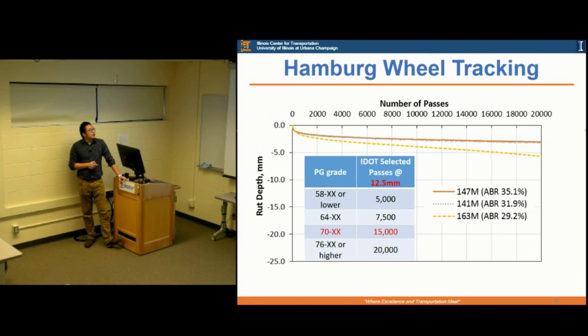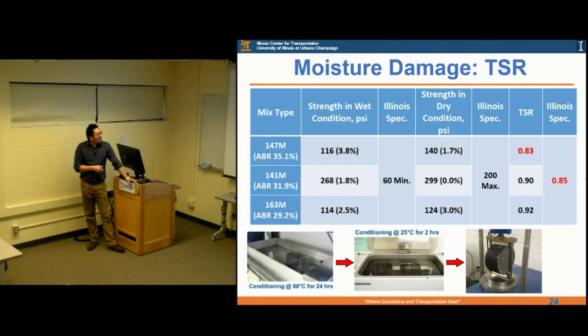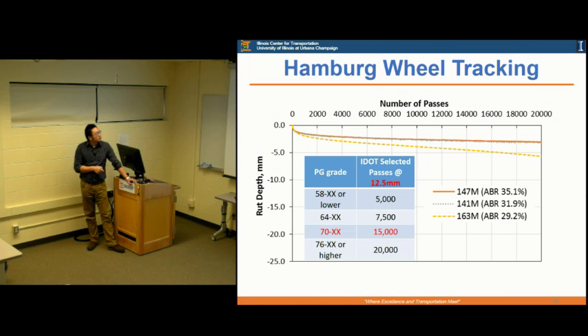This is the Hamburg wheel tracking test. I think IDOT uses this as the regular performance test. This is the number of passes versus the rut depth. IDOT had a specification on this, because the level binder you're using is PG70, which is polymer modified. Even though there's a little bit of difference between these two curves, the 163M has much higher rut depth developed than the other two.